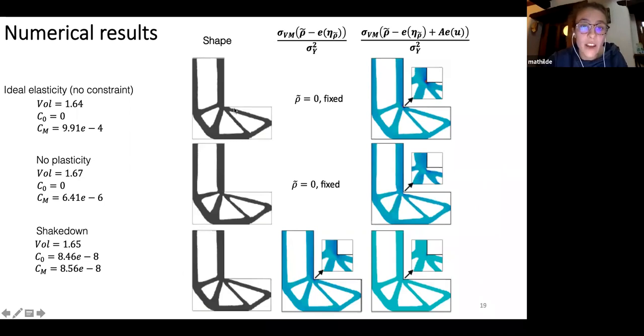And that's the same with the L bracket. So in ideal elasticity, we get the smallest volume. With non-plasticity constraint, that's the highest volume. And it gets rid of the material here to smooth. And in the shakedown constraint, we see that it creates a residual stress, which is non-zero, so that it can get an intermediary volume with well-satisfied elasticity constraints.